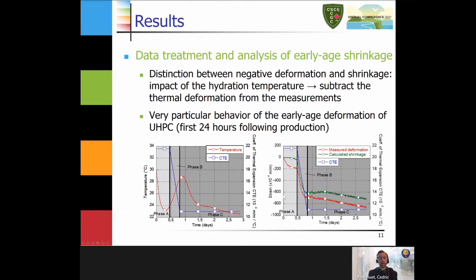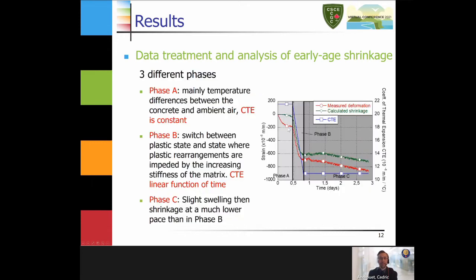And you see that we have a very particular behavior for the early age deformation of UHPC. Typically, the first 24 hours after the production are really specific. So we can separate that in three different phases. First, the phase A. Typically, what happens during the phase A is mainly related to differences in temperature between the concrete and the ambient air.